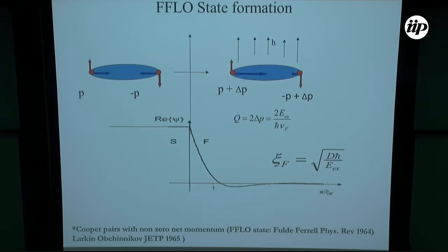This essentially produces oscillations in the superconducting order parameter in the ferromagnet, right? I will not go much into detail about that, but there are many interesting effects taking place here. That includes that if you do this with different thicknesses of the ferromagnet, you will get an oscillatory behavior in the transition temperature depending on the thickness of the ferromagnet, okay?